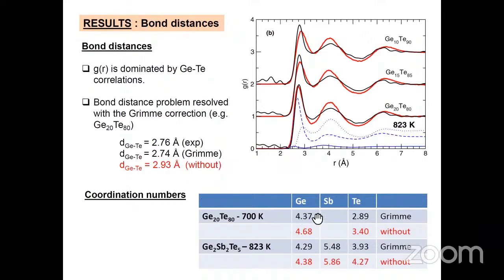And so the corresponding coordination numbers in those typical systems, of course, with the Grimme correction, will be reduced with respect to their counterparts from the red lines when we don't take into account those corrections.